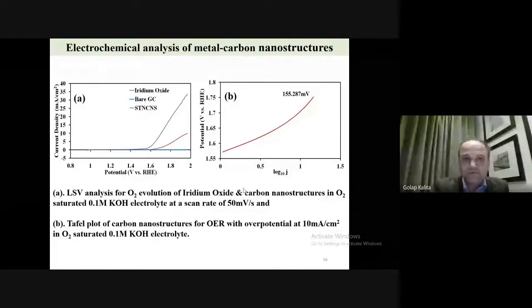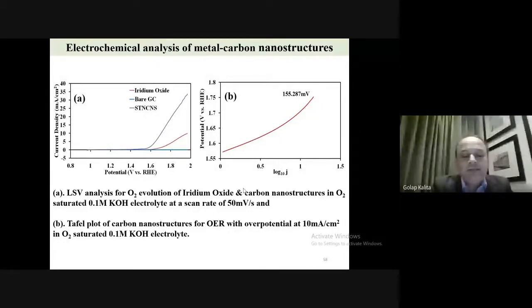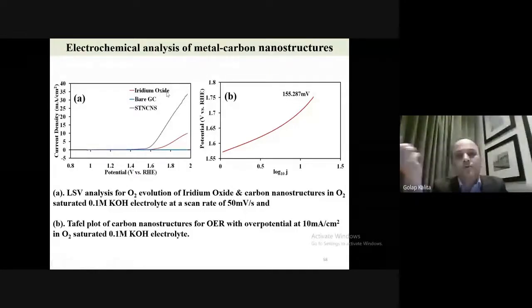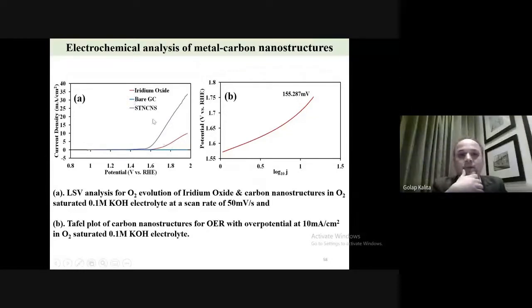Okay, then what we do is we study this OER reaction. In OER, iridium oxide, iridium being a noble metal, is one of the best OER catalysts. So this is commercially available iridium oxide, and our catalyst is much better in terms of onset potential and in terms of current density as well. So we are expecting very good results in this direction. We can have maybe much better catalyst.